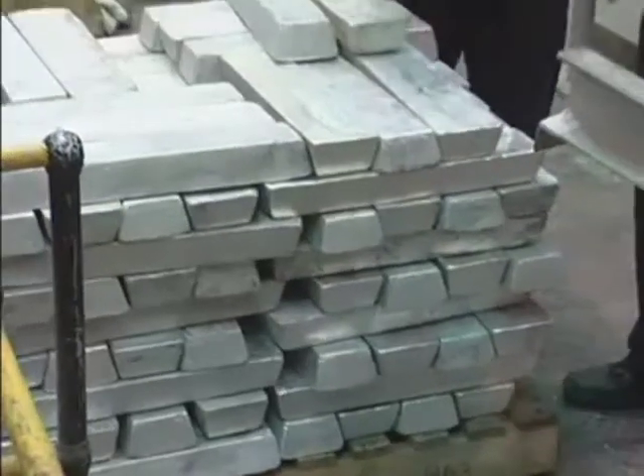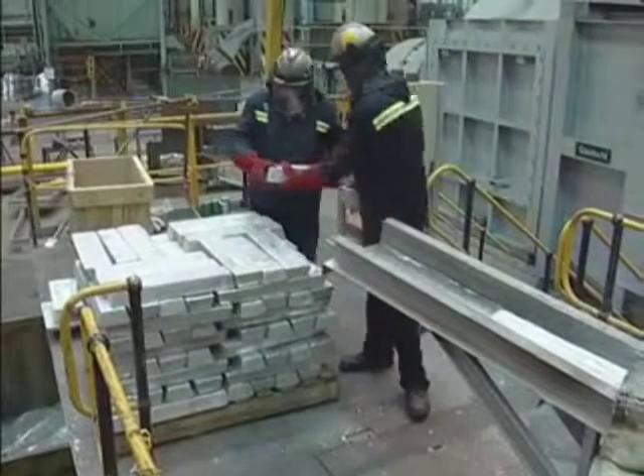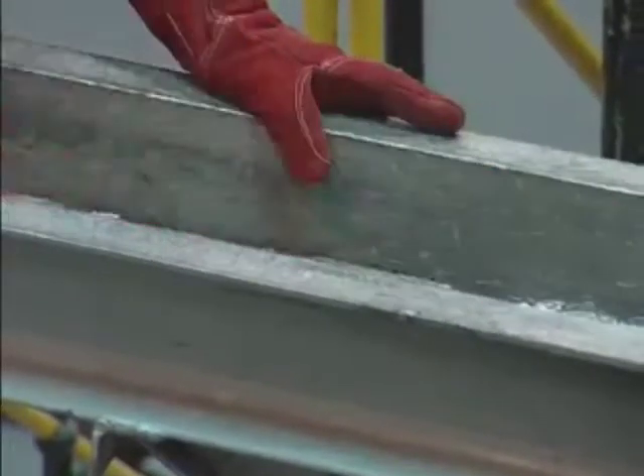Our biggest challenge then was basically alloying magnesium. We went through different options of trying to maximize our yield, get improvement in terms of metal quality, etc. And we believed, and I think have proven since, that the choice of an EMP was the correct choice. We were looking at an average of about 85% recovery of magnesium. We improved recoveries quite significantly when we added magnesium through the EMP. We started off, obviously, on a learning curve. We started off at around 95%, an improvement from 85, which was quite significant in itself, and we were able to do up to 98% plus in some instances.